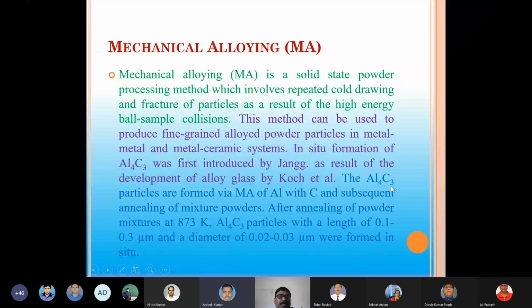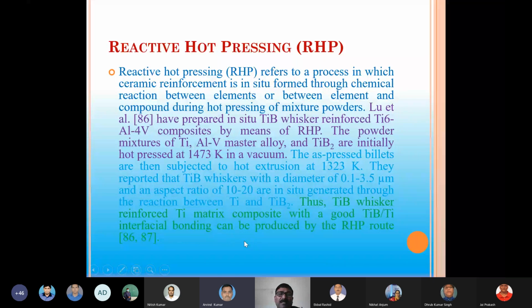Aluminum carbide particles are formed by mechanical alloying of aluminum with carbon and subsequent annealing of the mixed powders. After annealing of the powder mixture at a temperature of 873 Kelvin, aluminum carbide particles form, and the size will be 0.3 to 0.4 microns. Reactive hot pressing, by hot compression: there are machines where you take the powder and compress it, and then also you can get these composite materials.